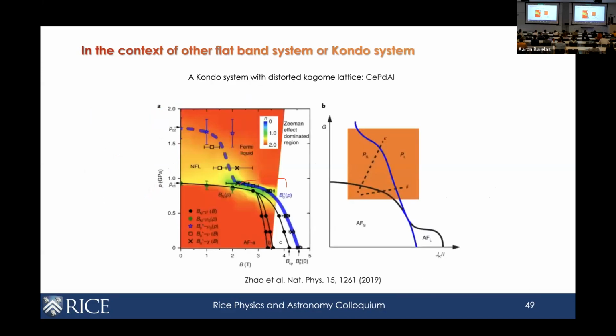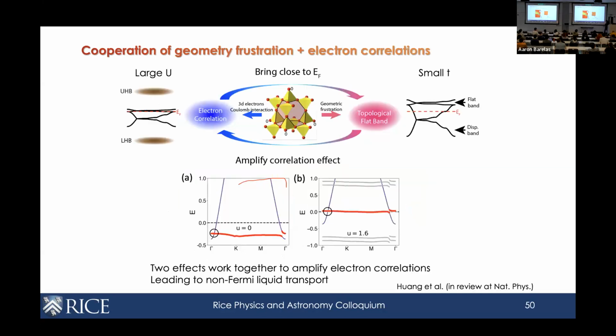To make a long story short, this is very analogous to some of the heavy fermion systems, where you have both very flat f electrons and dispersive states. Except in this material, it's a pure d electron system, and everything is from d orbitals. We have a flat band produced by both quantum interference effects as well as correlation effects, but it has resistivity behavior reminiscent of that in these heavy fermion systems.